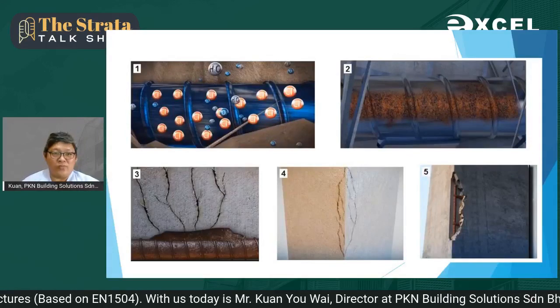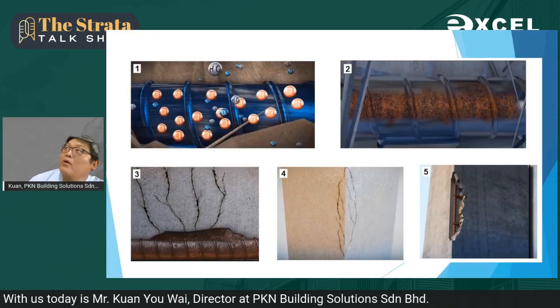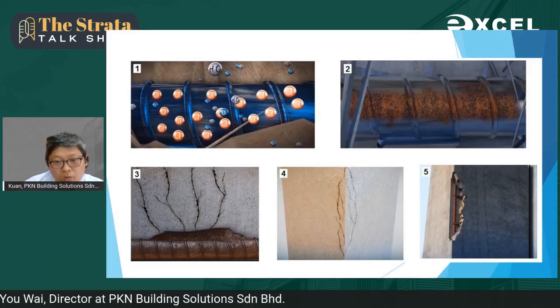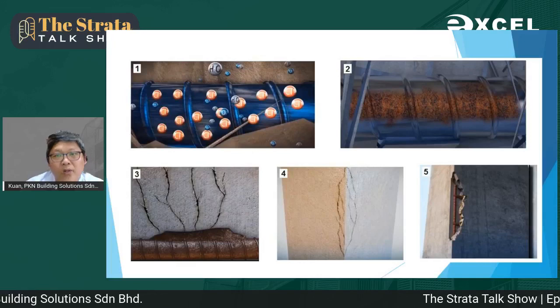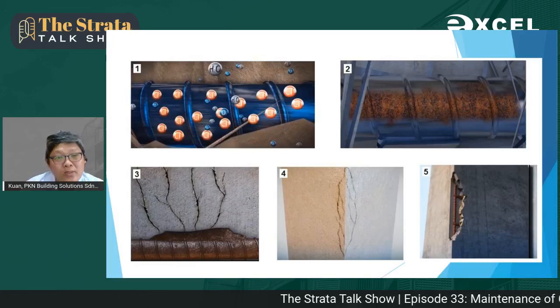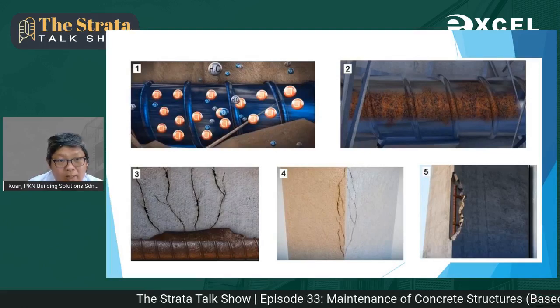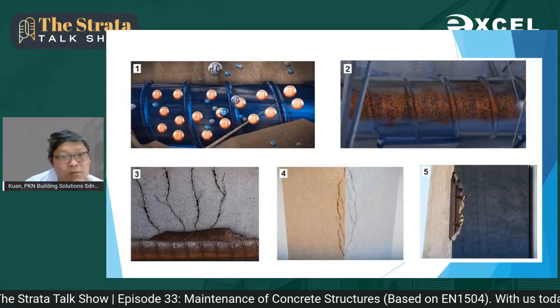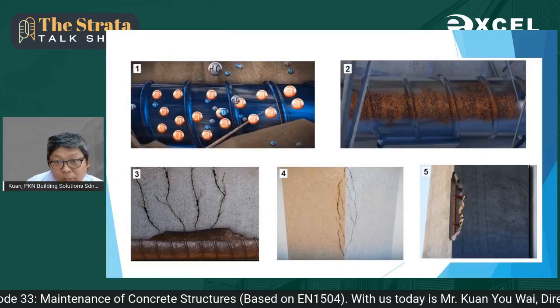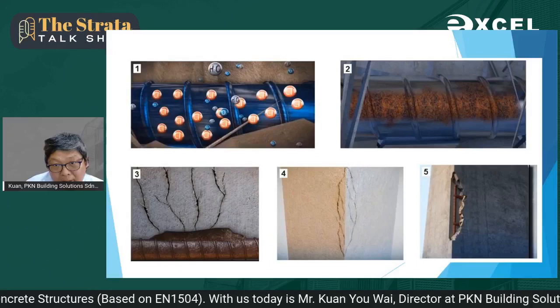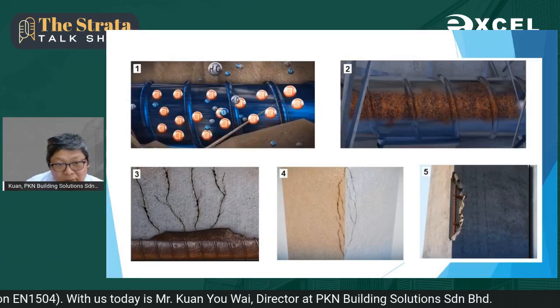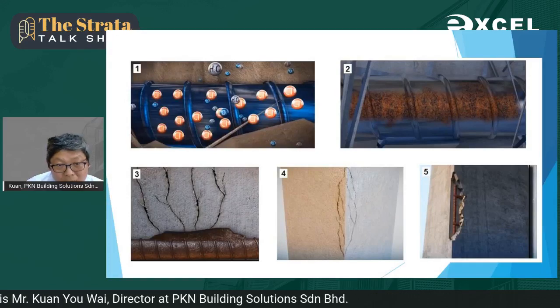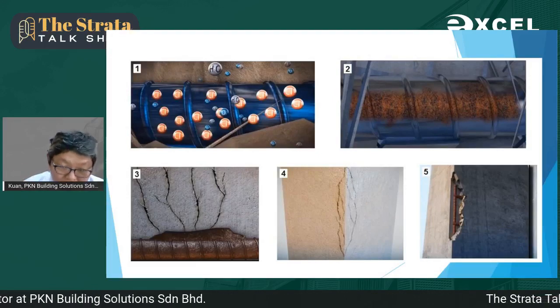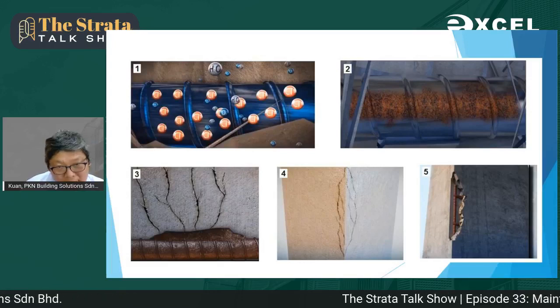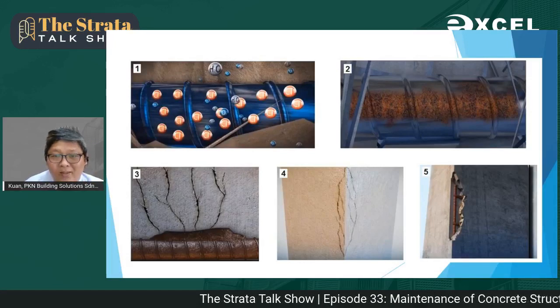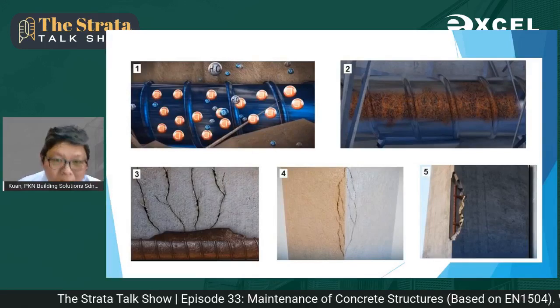And this is how it actually works. If you go to YouTube and type concrete corrosion, you will find a video animation that shows that once the chloride ions start to infuse into the concrete and reach the reinforcement steel bar, they will trigger corrosion, and the byproduct, rust, will crack the concrete because of the increase in volume. Once the concrete is cracked and eventually pops, you will see the rusty reinforcement steel bar on your structural element.